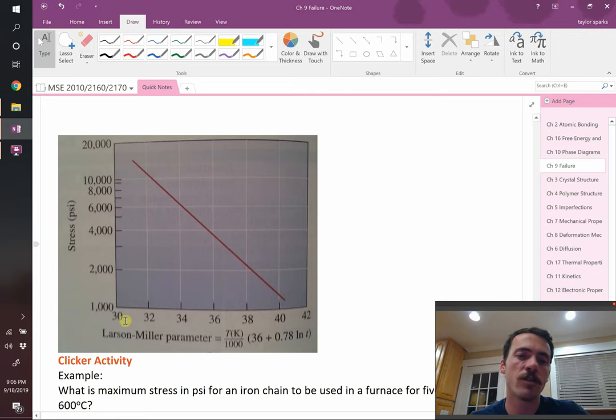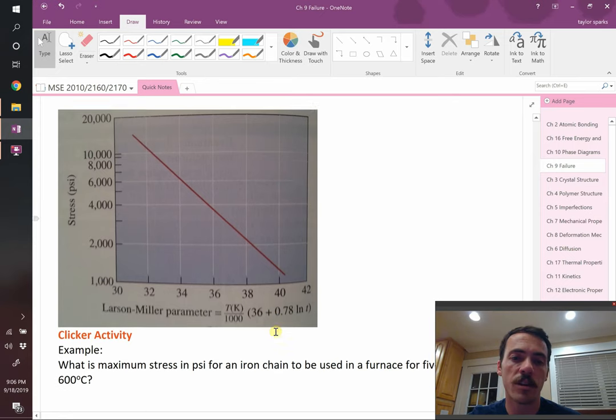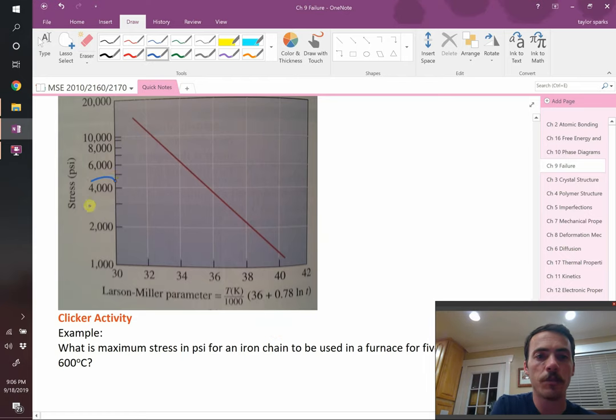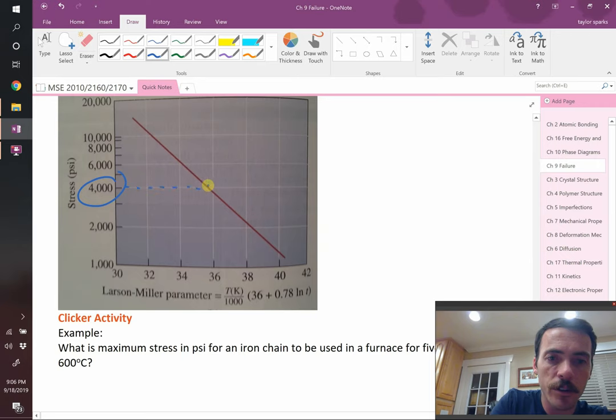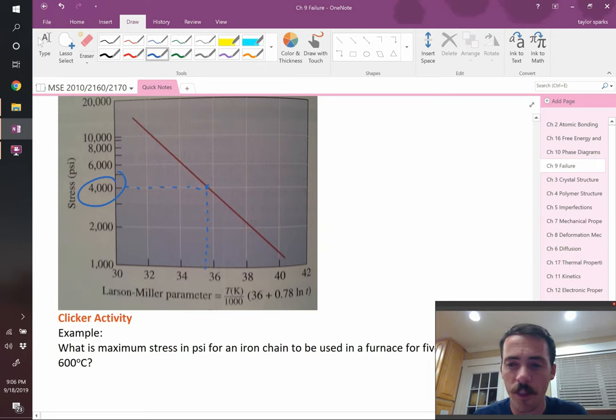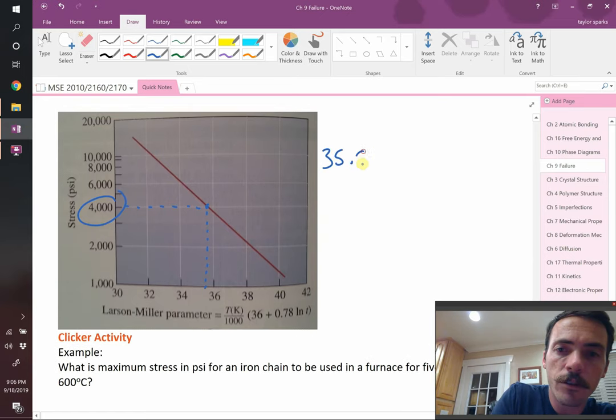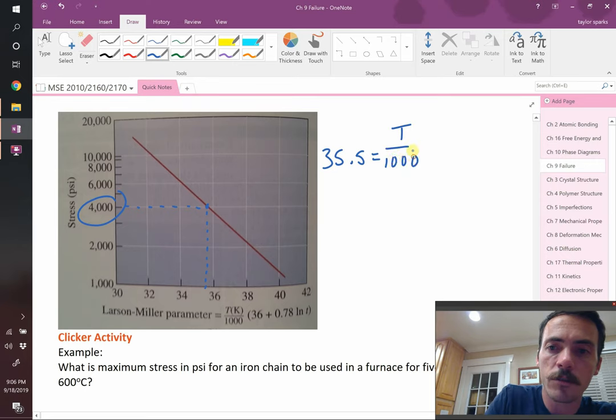And then down here, here's your Larson Miller parameter. And for this material, A is 36 and B is 0.78. What's really cool about this is you can then use this. You can say, okay, I'm going to load it at, say, 4,000 psi. Therefore, my Larson Miller parameter intersects this line right here at a value of, I don't know, call it 35.5. So you could plug in 35.5 and have that be equal to some temperature over 1,000 in Kelvin